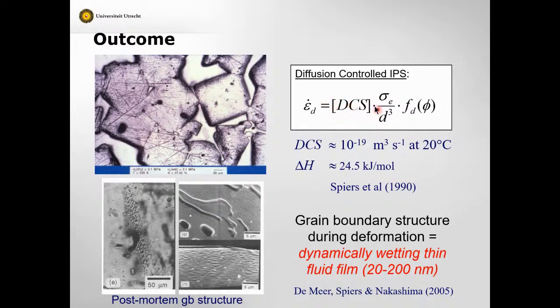This is the rate of diffusion in the grain boundaries. We could measure it, we could quantify it, we could quantify the temperature dependence, and we were able to observe that the grain boundaries were definitely coated with fluids in various kinds of experiments.